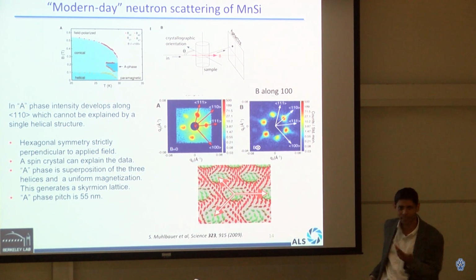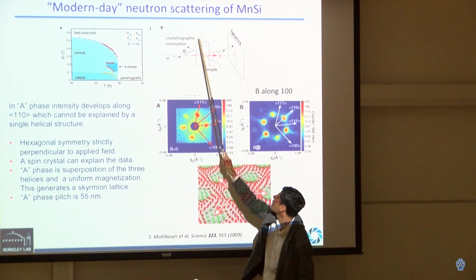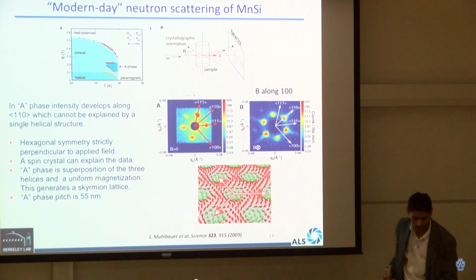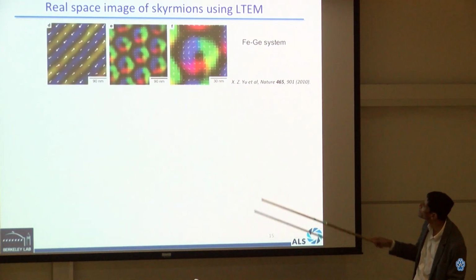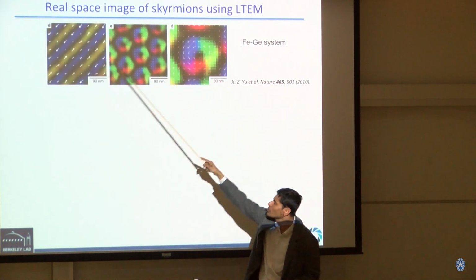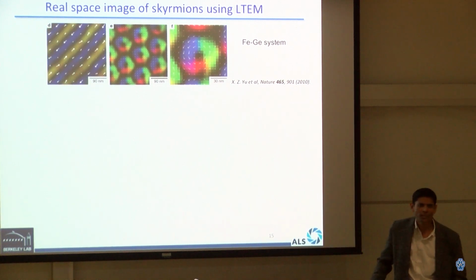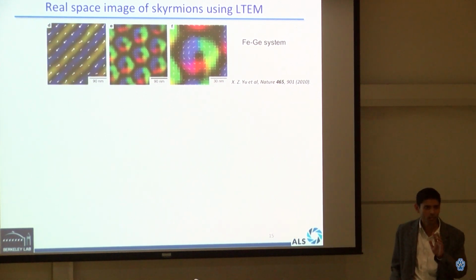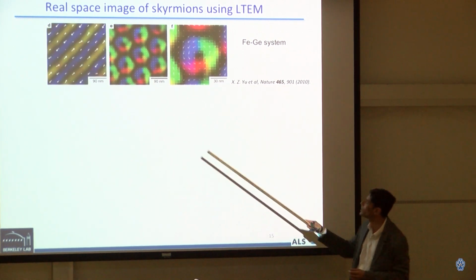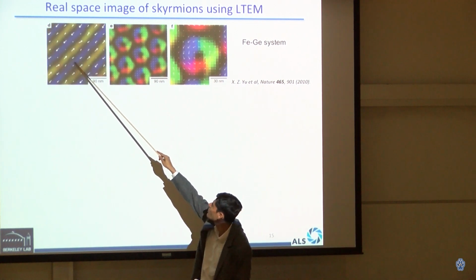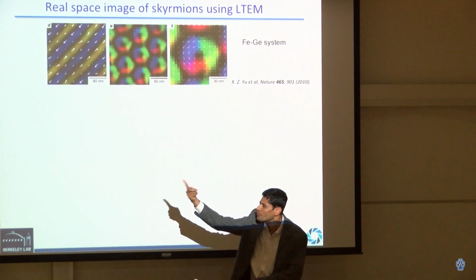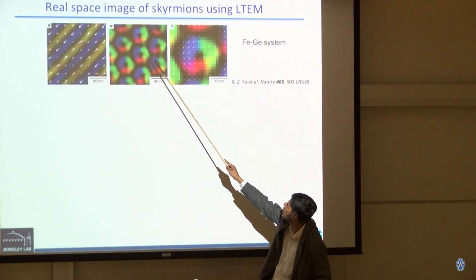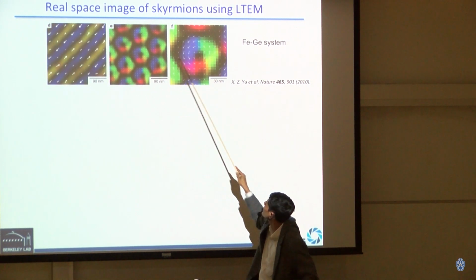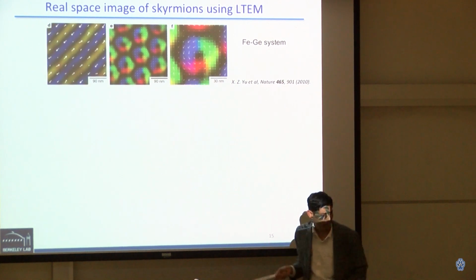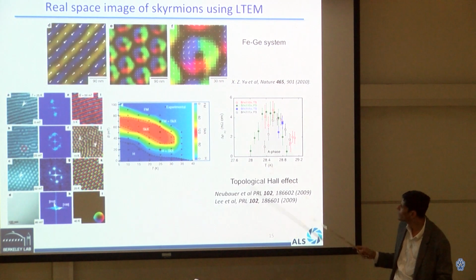Why did they get it and others didn't? That's the reason, because everyone was applying the field here and not in that direction. Then Tokura came, and his group did very good LTEM, a transmission electron microscope in the Lorentz mode, where you can map out the B field, the induction field, of the spin texture of the material. They showed that there is this helical phase, a staircase of spins, and then that morphs into a skyrmion hexagonal lattice, and this is one of the zoomed-in images of the lattice. Then they did all kinds of phase diagrams and everything else, and the topological Hall effect.